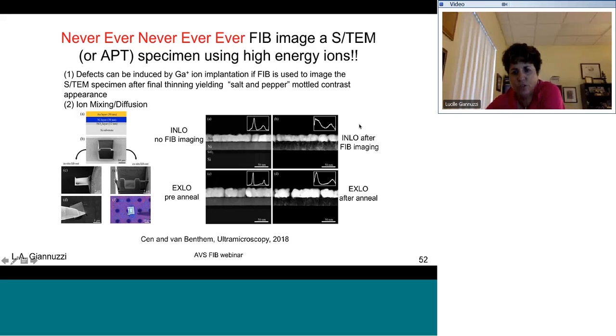So what this shows you is in-situ lift-out after FIB imaging gives you similar results to ex-situ lift-out after the annealing experiment. And so without even doing the annealing experiment, you get ion implantation damage and basically interdiffusion due to the ion implantation that looks like what your heating experiment looks like.